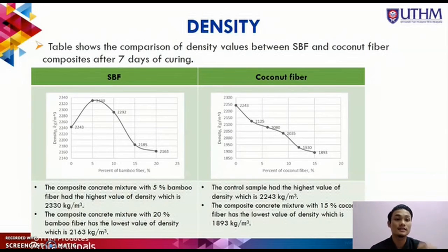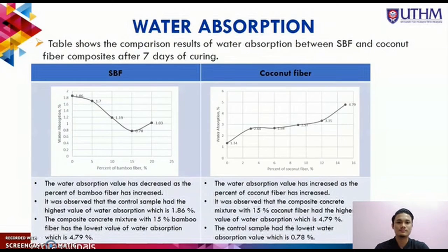For the next tests such as density, water absorption, and compressive strength, the results will be compared between SBF and coconut fiber after 7 days of curing from previous research. The density comparison found similarities between SBF and coconut fiber, because the density value decreased as the percentage of fiber increased. For the water absorption result, the comparison found a difference between SBF and coconut fiber. The water absorption value for SBF decreased as the percentage of fiber increased, and the opposite for coconut fiber.